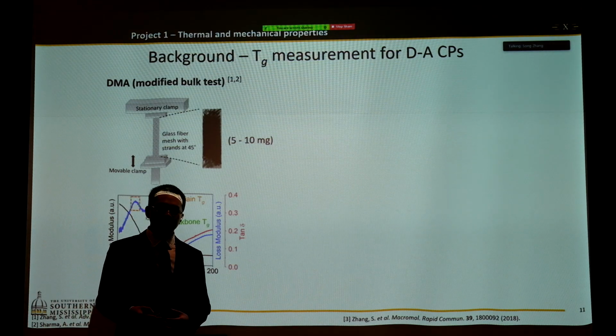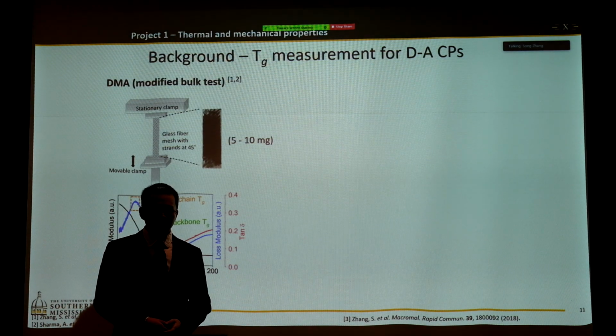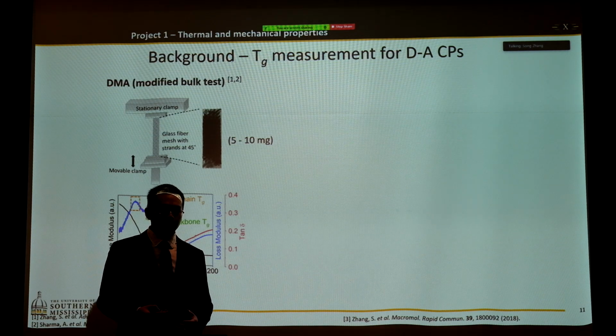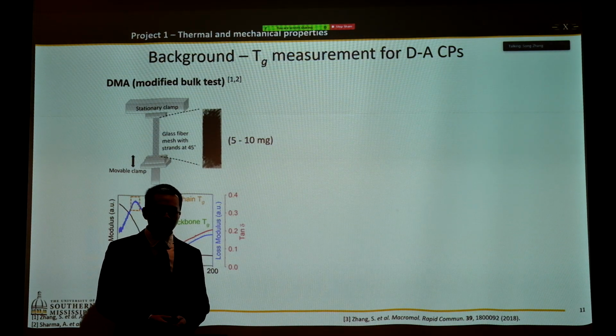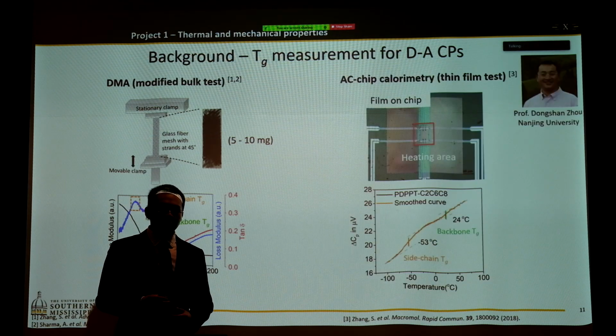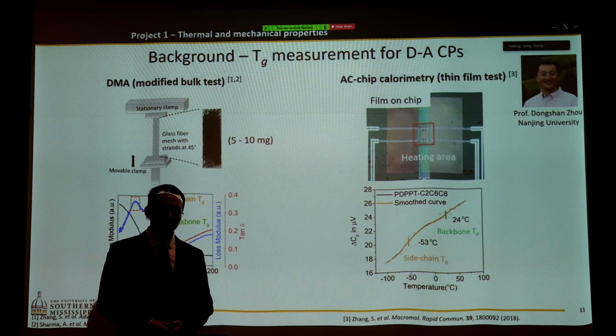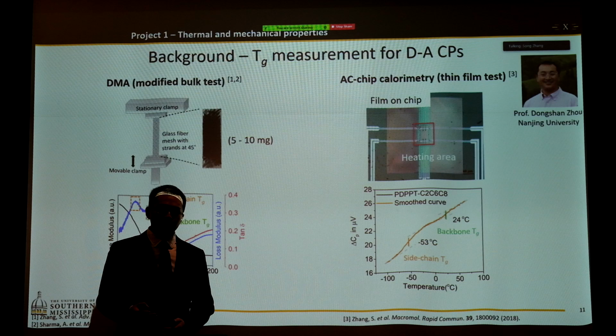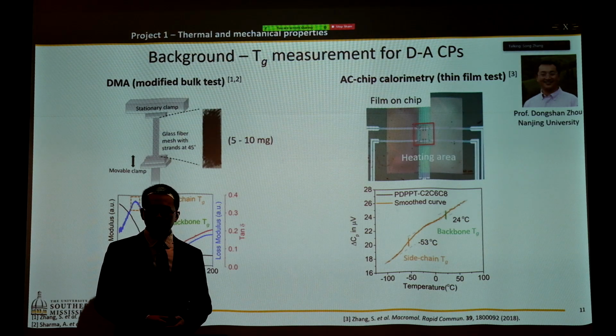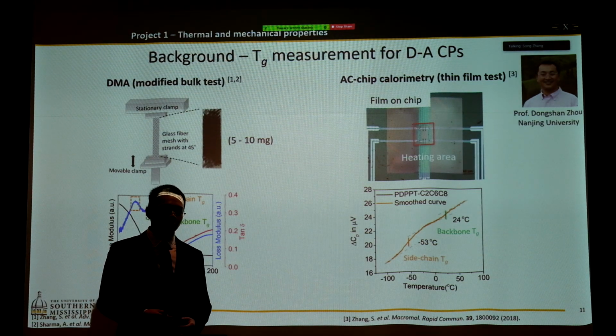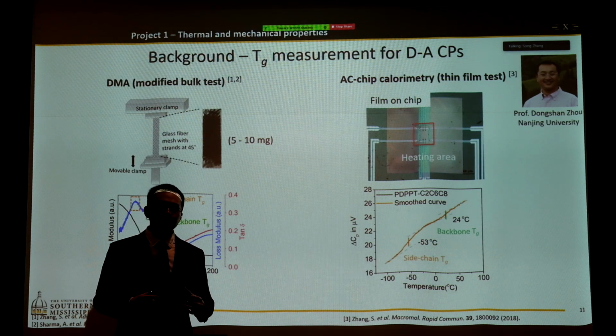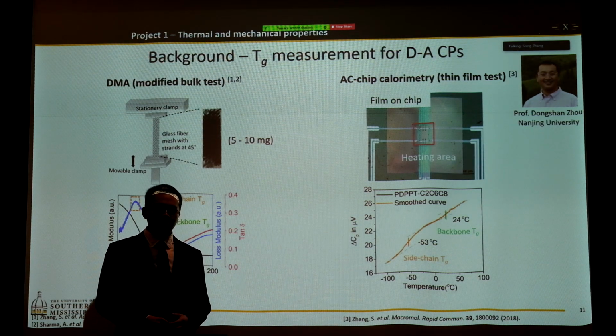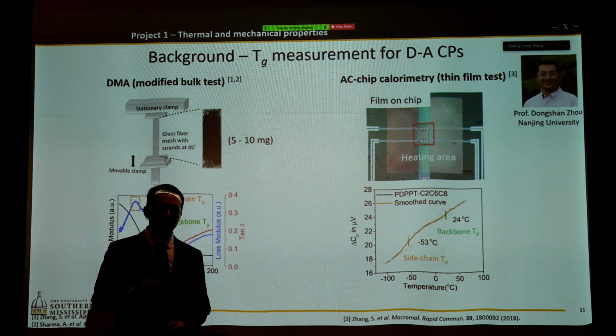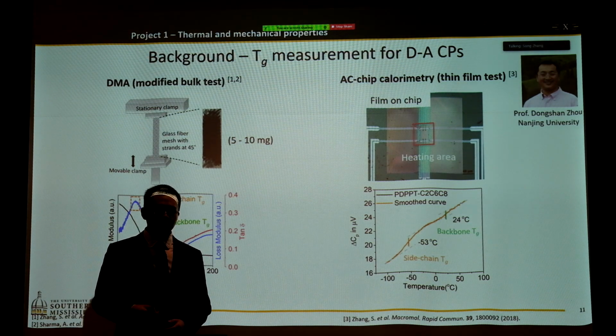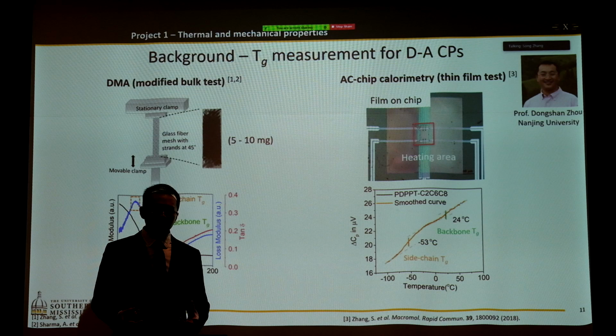One is around -50 degrees, another is around 25 degrees Celsius. And in the future slides, I will only report the tangent delta Tg. If we want to understand the thin film Tg, it is also doable. We collaborate with Dr. Zhou in Nanjing University, who has a very specialized technique called AC chip calorimetry. And this is much more sensitive than the traditional DSC and can extract the step change very efficiently. And as you can see here, the Tg corresponds well with the DMA result.